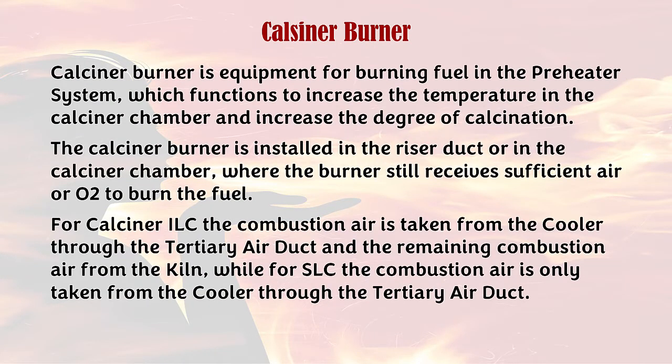The calciner burner is equipment for burning fuel in the preheater system, which functions to increase the temperature in the calciner chamber and increase the degree of calcination. It is installed in the riser duct or in the calciner chamber, where the burner receives sufficient air or O2 to burn the fuel. For the calciner ILC, combustion air is taken from the cooler through the tertiary air duct and the remaining combustion air from the kiln. For SLC, combustion air is only taken from the cooler through the tertiary air duct.